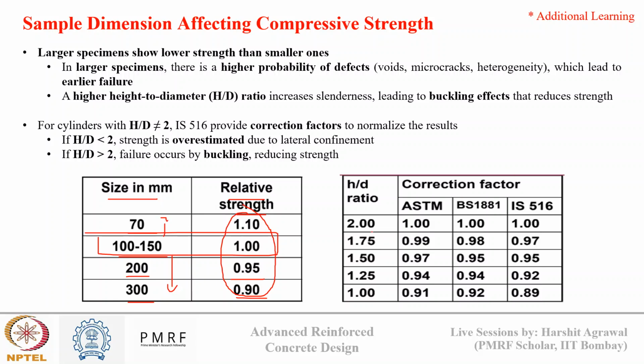For cylinder also, based on H by D ratio, ASTM, British Standards, and IS code provide different correction factors for strength. If my H by D ratio is lower than 2, then strength is overestimated due to the lateral confinement. We will see that the weak failure plane present in between reduces, so we get an overestimated strength. However, if the H by D ratio is more than 2, then buckling failure can occur, which will reduce the strength. And that is reflected in the correction factors that we see here.